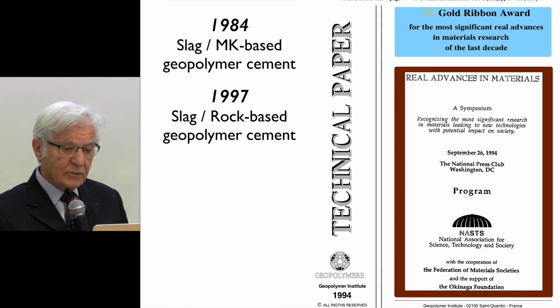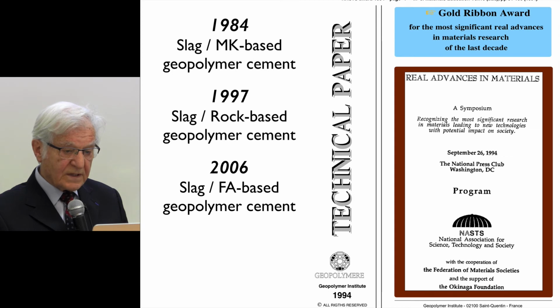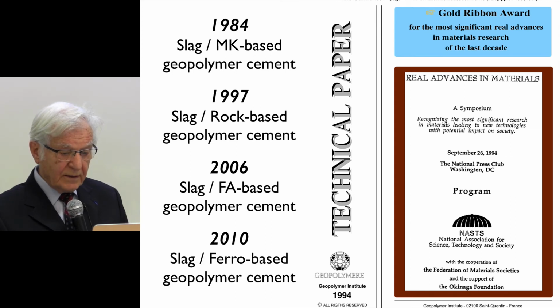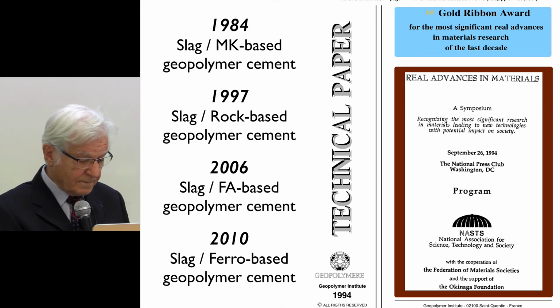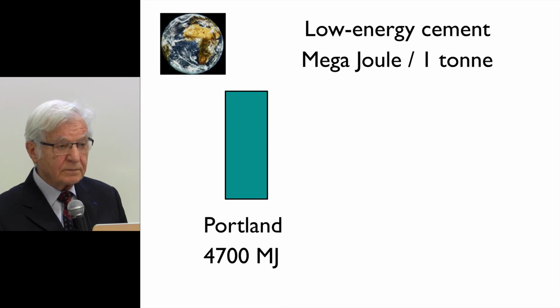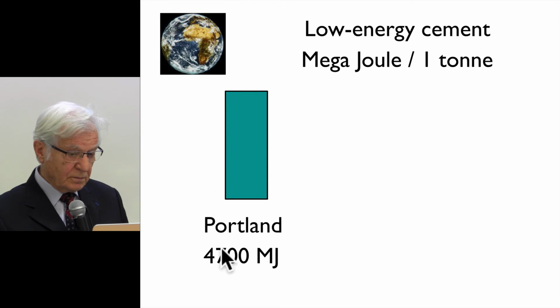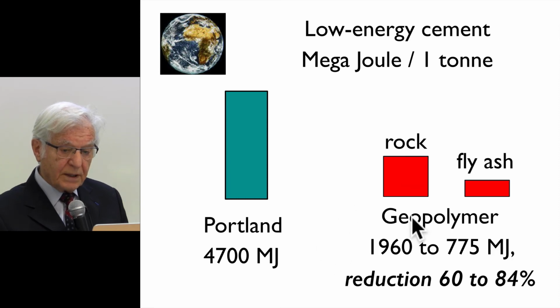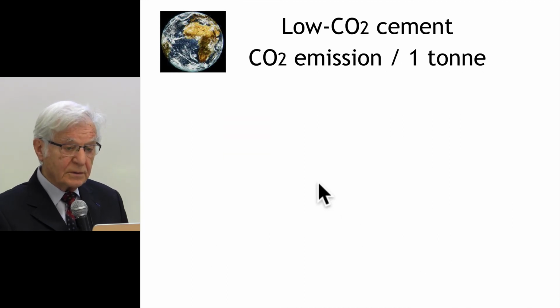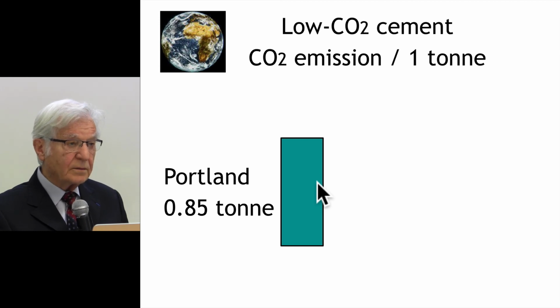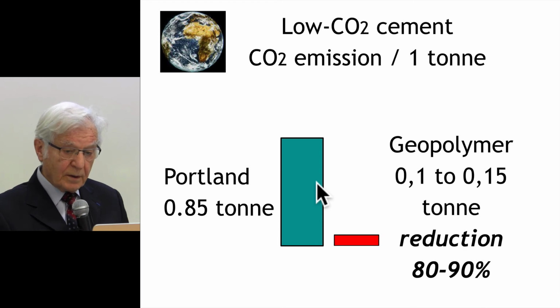1997, invention of the slag rock-based geopolymer cement. 2006, invention of the slag fly ash-based geopolymer cement. 2010, invention of the slag ferro-based geopolymer cement. If we compare the energy needed for making 1 ton of Portland cement, we need 4,700 megajoule per ton. For a rock-based geopolymer, we need 960, and for fly ash-based, 775 megajoule, which is a reduction by 60 to 84%. If we compare the CO2 emission, Portland 0.85 ton per ton of clinker, geopolymer 0.1 to 0.15, which is a reduction of 80 to 90%.